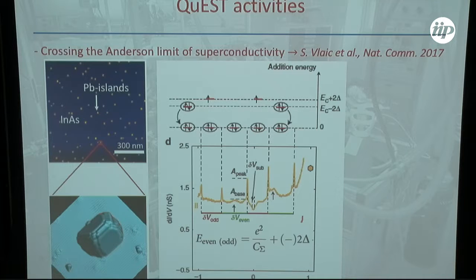Each time you charge, you pay charging energy, and that gives you these peaks in the tunneling characteristics. But in addition, you pay the so-called parity energy. If the number of electrons sitting in the island is odd, then putting one more electron is easier than when the number is even. It's because the electrons are bound. And so the distance between two peaks is 2 times the charging energy plus or minus 2 times delta.